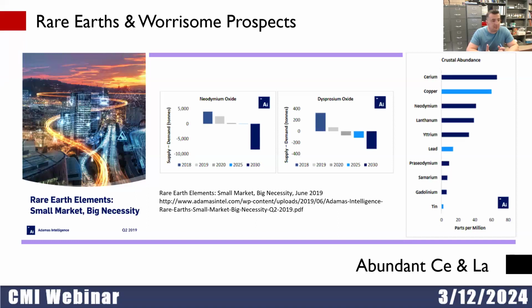And neodymium is basically the main element needed for permanent magnets, for neodymium iron boron. Neodymium, but also dysprosium. So by 2030, allegedly, it seems like we will be out of neodymium and dysprosium. But the market and the applications will grow, electrification will grow. So we would need something that will substitute them. What can substitute them? And when we look at the rare earths, cerium and lanthanum are in great abundance. There is no problem with that.